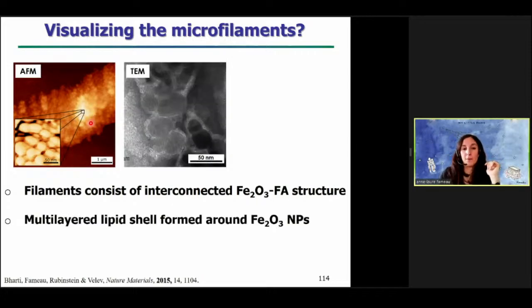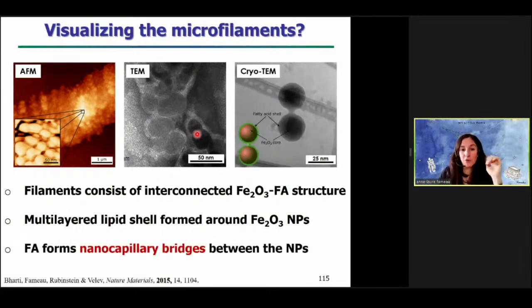Then we use TEM experiments. We stain the fatty acid solution before with uranyl acetate. And now the fatty acid appears in white, as you can see here, and the nanoparticles in black. And you can clearly see that each particle is surrounded by a thick shell of fatty acids. Then we have a closer look by cryo-TEM, and you can clearly see that between two nanoparticles, you have the formation of capillary bridges. And you can see that the fatty acid shell seems to be quite fluid surrounding the particles.